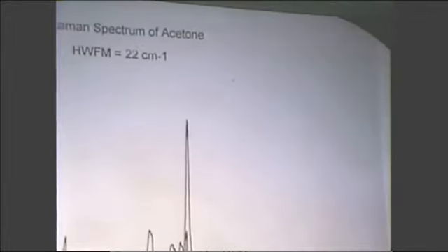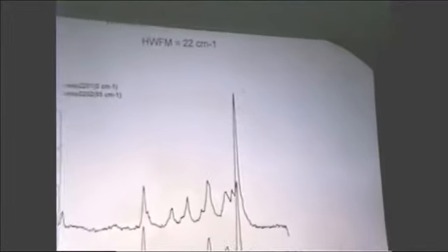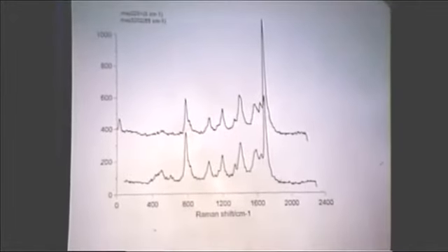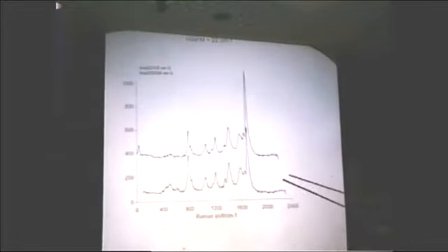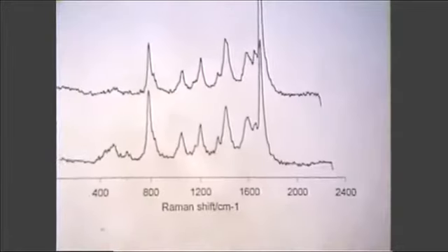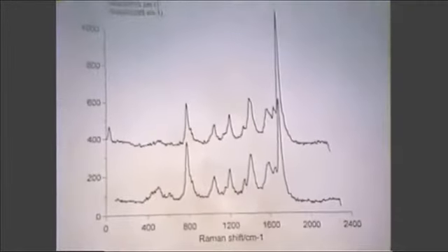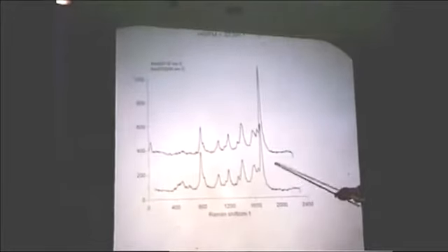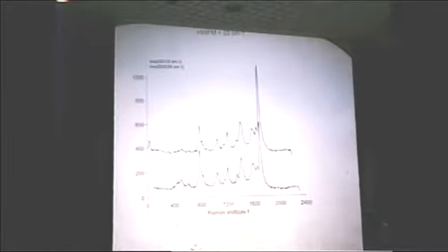Just to give you an example of the first spectrum that we ever measured. The first thing you do is you measure something easy. And this is just an example of a spectrum of acetone that we measured. The resolution at the time when we were measuring this spectrum was about 22 wave numbers. So it isn't terrific, but at least it's in the vibrational resolution regime. And of course we get a nice pattern of peaks from acetone, and it looks something like the literature spectrum for acetone.